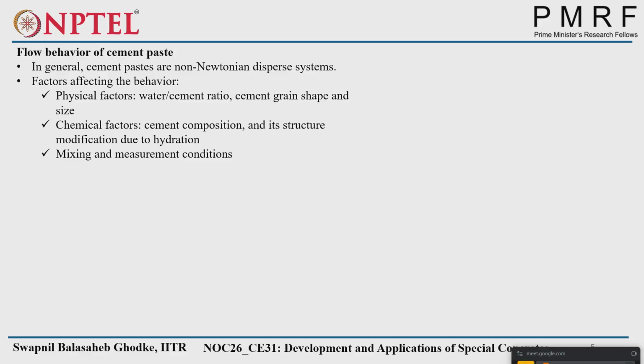Shear history means the shearing of the material during mixing. If you mix at a higher speed, there is a possibility of higher hydration or higher heat generation. That's why the material will stiffen as early as possible and it will show higher yield stress and plastic viscosity at the time of testing. So both mixing and measuring conditions, and the measuring equipment, are very important.